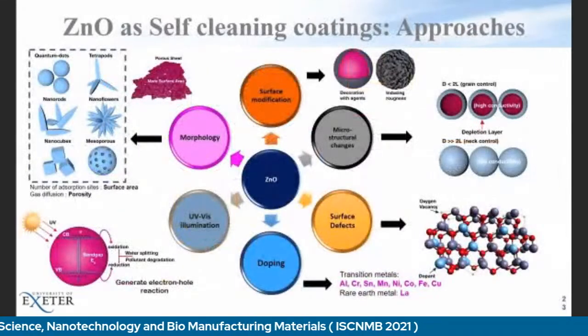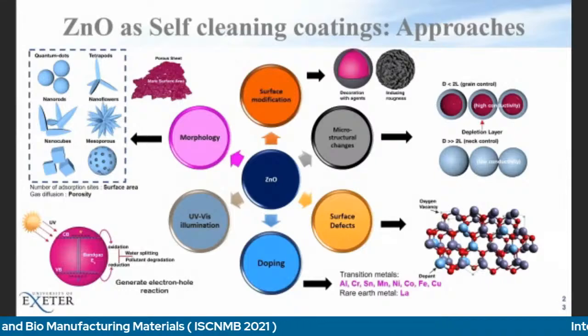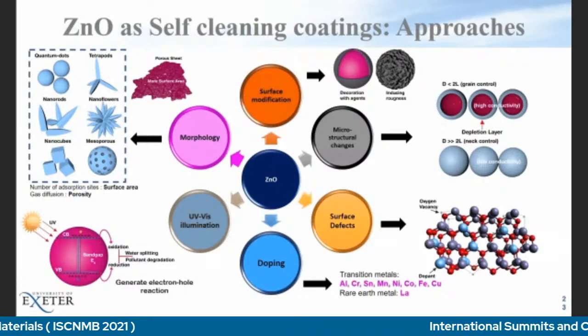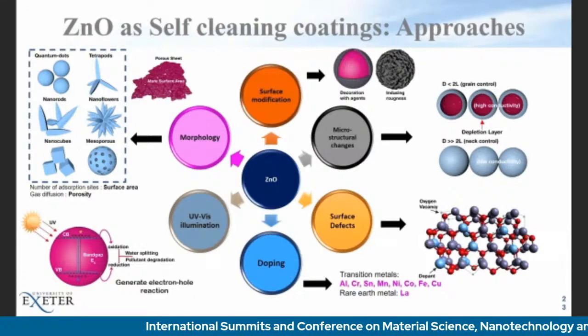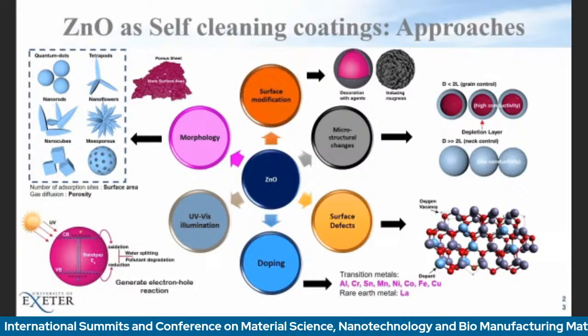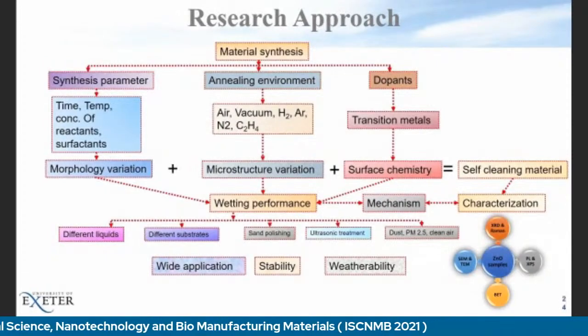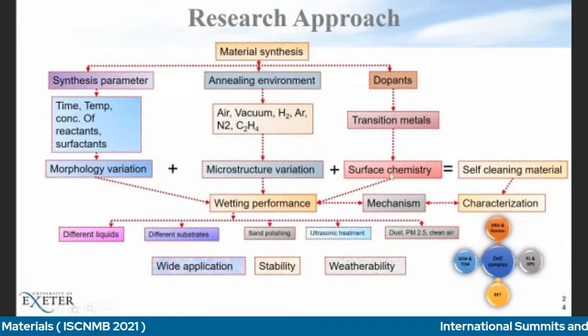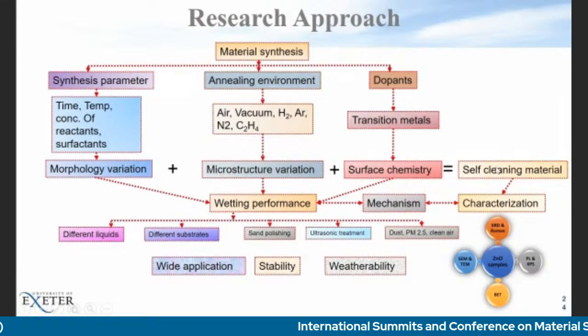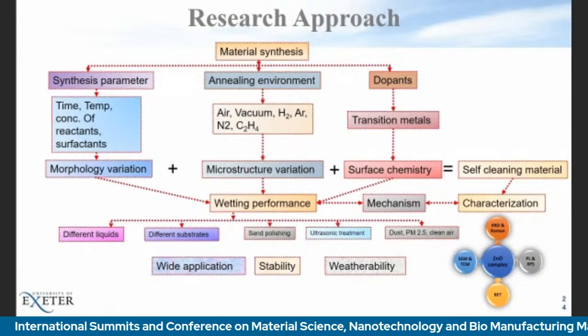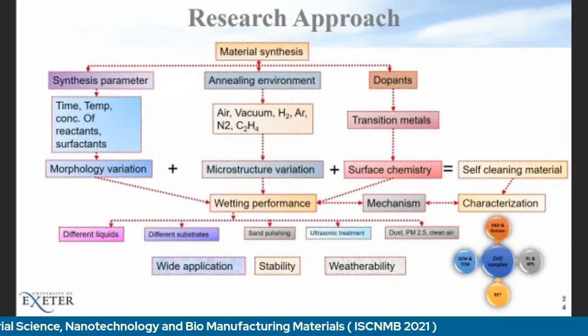Now, you can vary its self-cleaning property by modification of surface, by changing the morphology, by changing the UV visible illumination, by creating surface defects, or employing some doping agent, or you can change it with microstructural changes. In our case, we have tried varying the morphology, the microstructure and the surface chemistry, and then we found out what self-cleaning materials we can have. And then we did the different characterizations such as XRD, AFM, and all those. But yes, we are still away from doing the real-time test with the photovoltaic system.